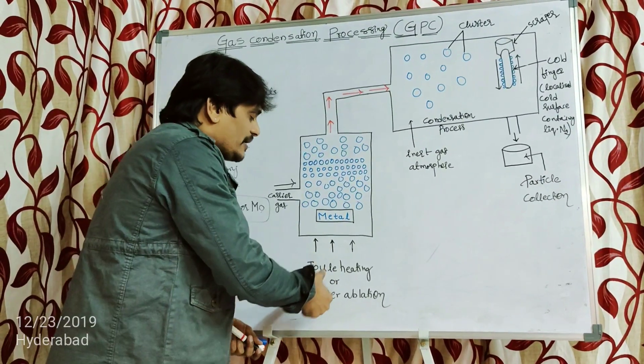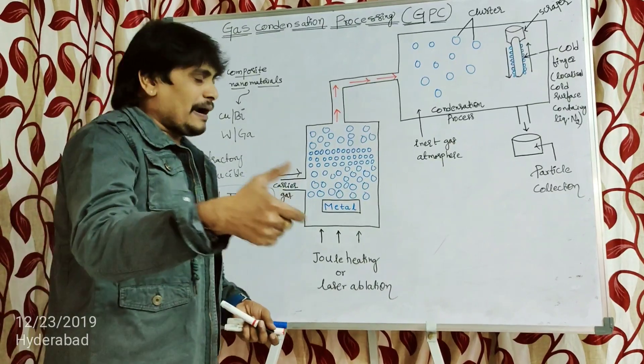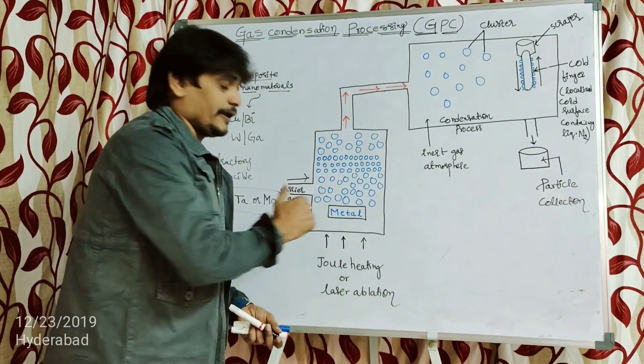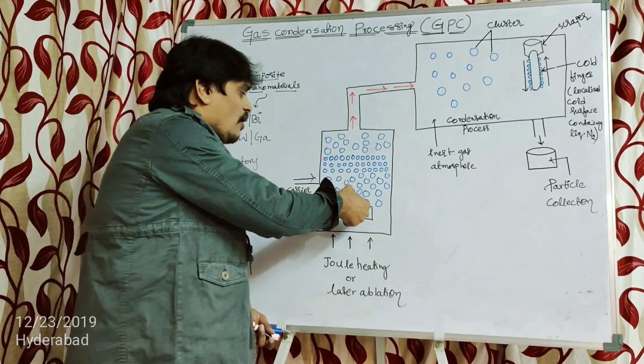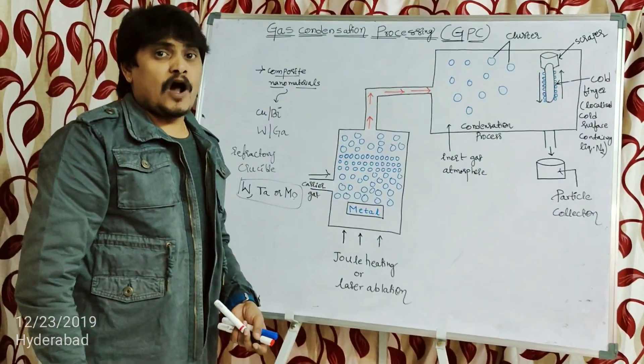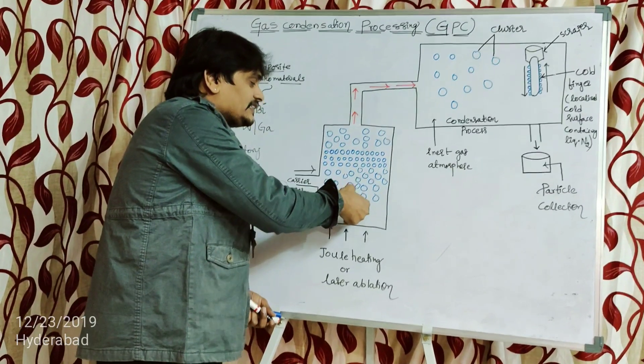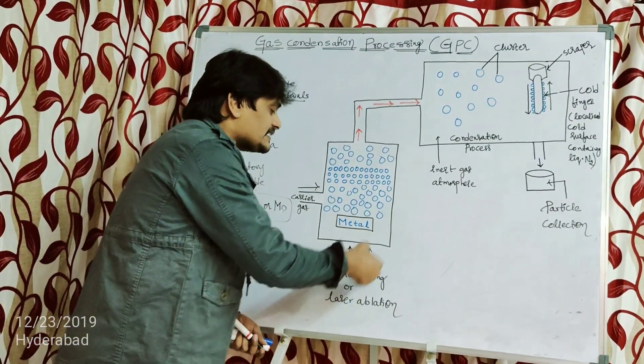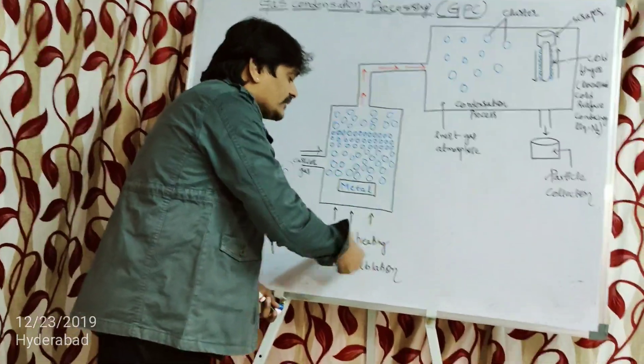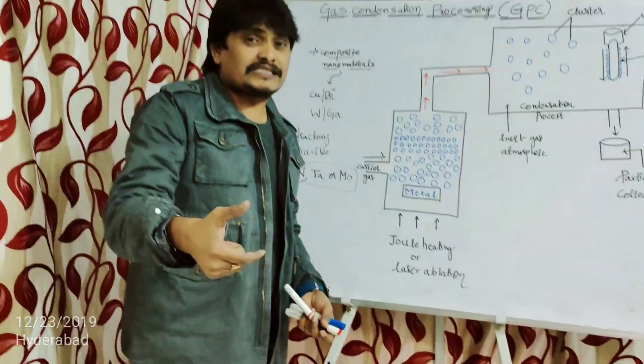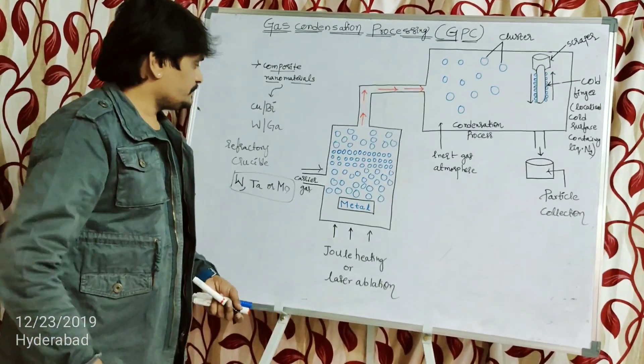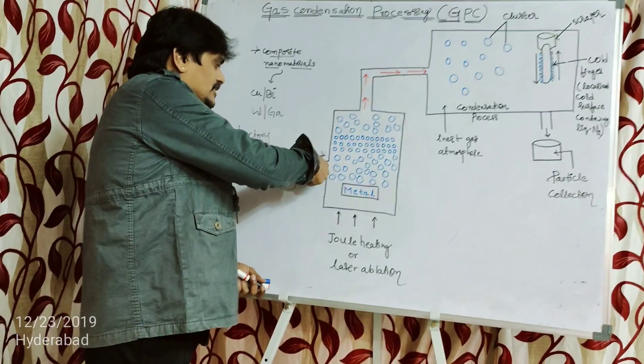Generally, in this method we use Joule heating. However, whenever the melting point of the metal in the refractory crucible is very high, or the metal is reacting with the refractory crucible, then we have to use laser ablation instead. So those are the conditions determining which heating method to use.